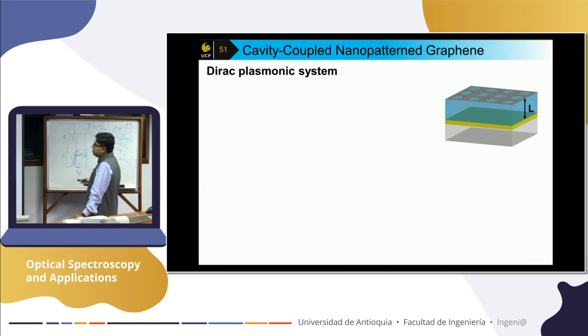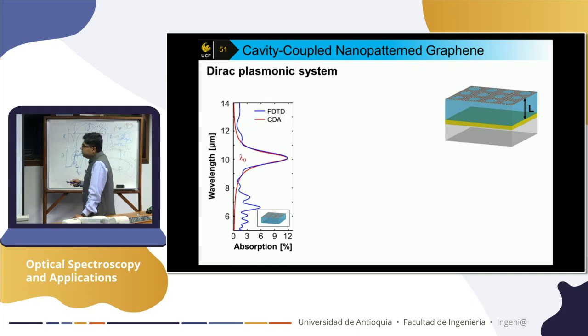We made patterns so that you can excite the surface plasmon of graphene, called the Dirac plasmon. Because it's a semi-metal, it has free carriers, so when you excite with light, you excite the graphene plasmon. Just look at this patterned graphene film. As soon as we control the pattern, we can excite a localized surface plasmon mode on those nano holes, and you can go from about 2% flat absorption to about 10% around 10 micron.